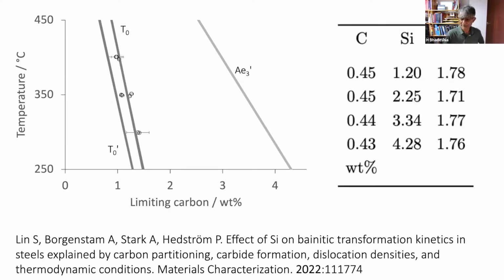And there are now a huge quantity of data to support the idea that the reaction stops at T0. These data were published this year by the group in Sweden. And they represent all these steels, but the T0 curves are all almost identical. You can see from the breadth of these gray lines. So this was published about, I would say, 3 weeks ago, and Google Scholar kindly notified me of this publication. It's a wonderful system, Google Scholar. So I plotted the T0 curves, and you can see that the data fall pretty accurately on the T0 curve. This is simply allowing for strain energy.